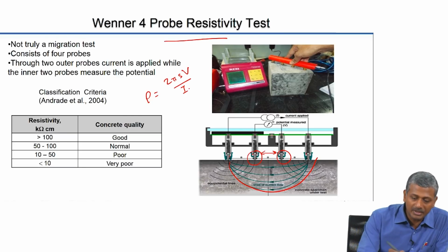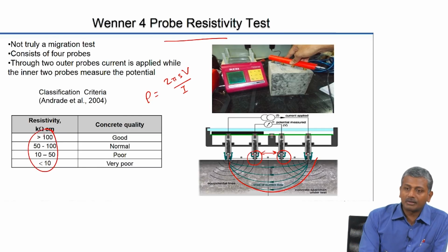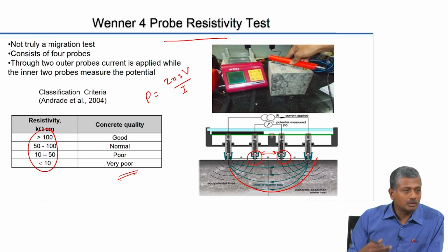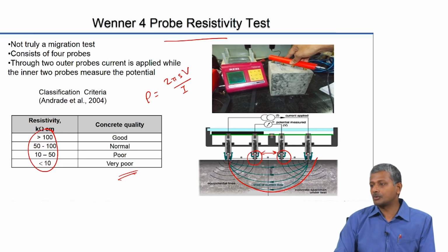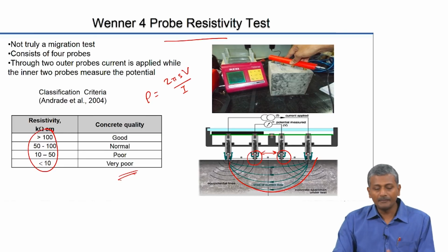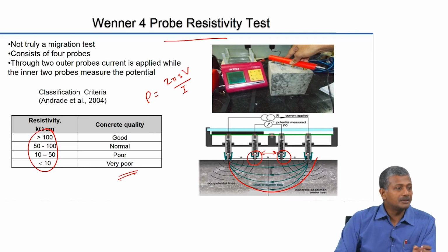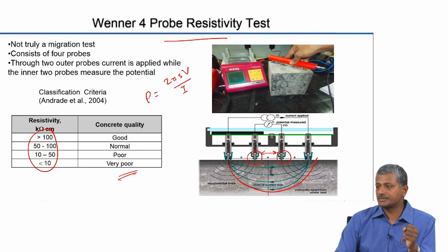So, you can use the same test to then classify your concrete in terms of resistivity with respect to how easy it will be for ionic species to flow in the concrete and lead to conditions of corrosion. So, again, resistivity gives you a direct measure of your permeability or interconnectivity of the pores in the system.